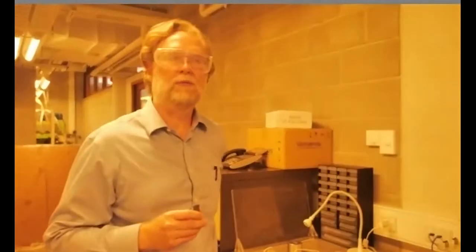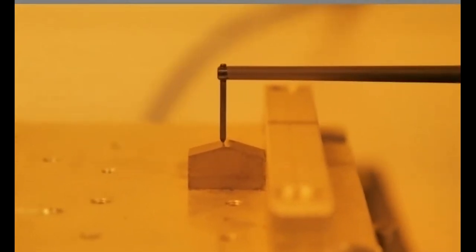Another very important part of understanding what's happening with these bearings is, again, measurement of the wear profile. The 3D profiler we showed you just before is accurate to about 40 micron. That's the 3D scanner. This TallySurf is much more accurate and works on a contact basis. So again, we have our little element there that we showed you in the Tribo lab representing a part of the bearing. And the TallySurf takes very accurate measurements, accurate to about 1 micron, to measure that wear profile.